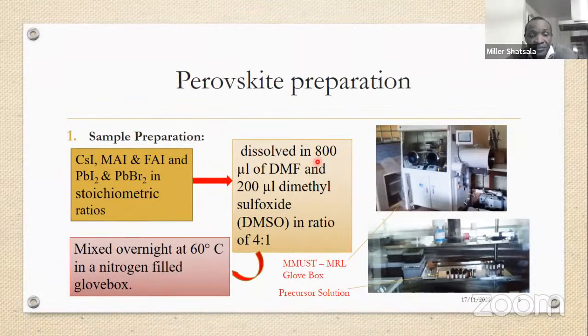Then we dissolve them in DMF and DMSO in the ratio of 4:1, that is 800 microliters to 200 microliters. Then we shall mix them overnight at a temperature of 60 degrees in a nitrogen glovebox. This is the nitrogen glovebox that we have been using in our lab. We call it the MMUST Materials Research Lab, where MMUST stands for Masinde Muliro University of Science and Technology. Then these are the precursor solutions.